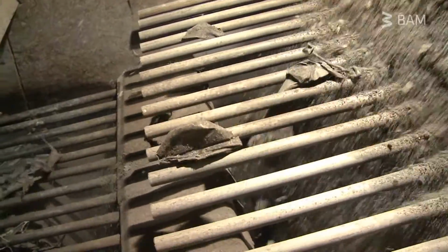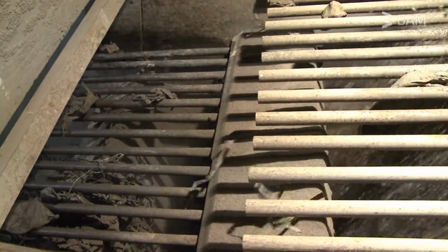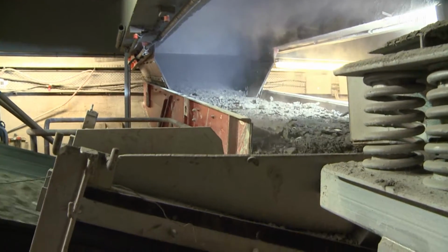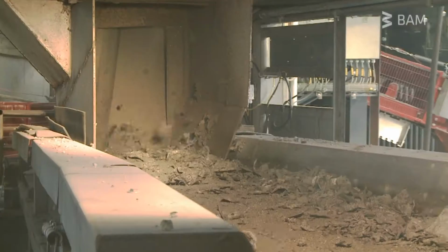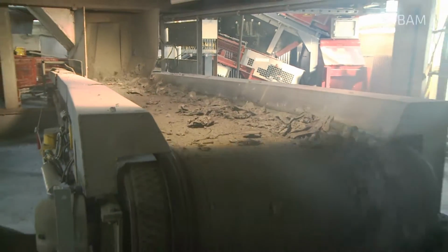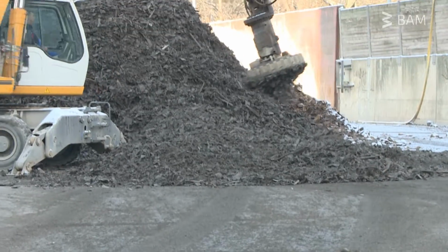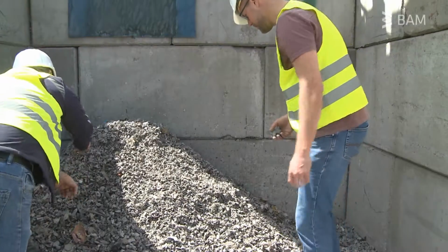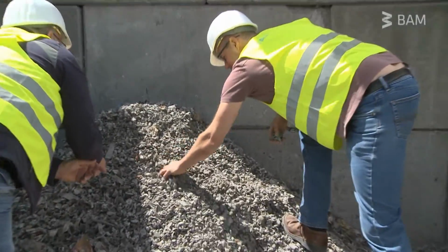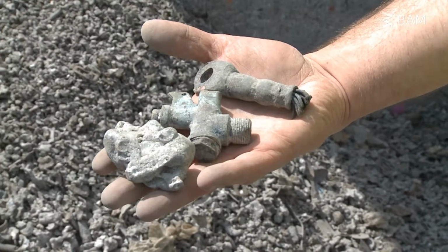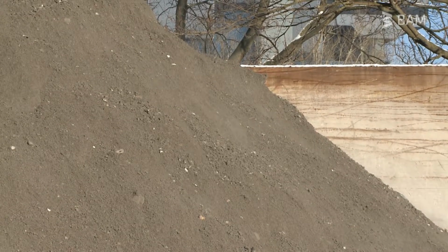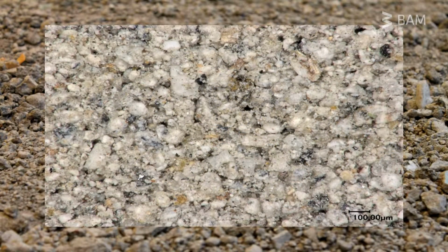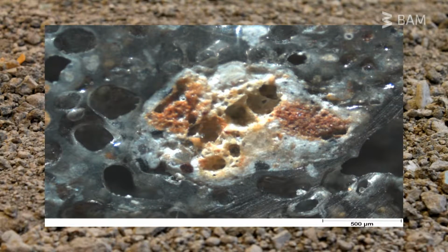Bottom ash is an inhomogeneous mixture consisting of mineral aggregates and metals, as well as small amounts of unburnt materials like stones, glass, ceramics and organic residues. The share of metals in bottom ash is around 10%, whereby ferrous metals are prevailing. A smaller amount of non-ferrous metals consists especially of aluminum and copper, as well as the alloys brass and stainless steel. About 80% of bottom ash is represented by mineral aggregates, comprising ash and slag particles in equal shares. Slags are vitreous or crystalline melting products.